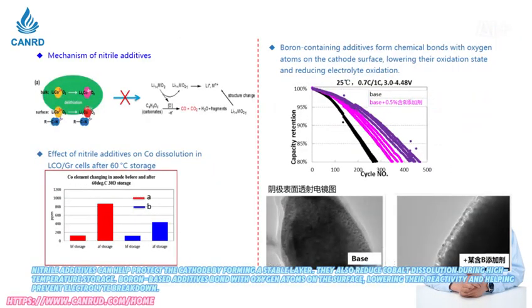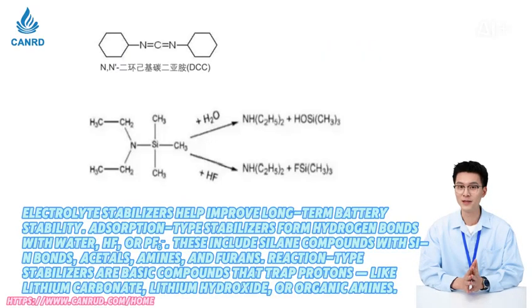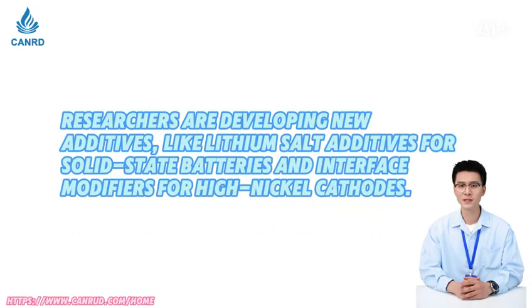Nitrile additives can help protect the cathode by forming a stable layer. They also reduce cobalt dissolution during high-temperature storage. Boron-based additives bond with oxygen atoms on the surface, lowering their reactivity and helping prevent electrolyte breakdown. Electrolyte stabilizers help the battery last longer. Some block water and acid, others catch harmful particles. This keeps the electrolyte stable and the battery safe. Researchers are developing new additives, like lithium salt additives for solid-state batteries and interface modifiers for high-nickel cathodes.